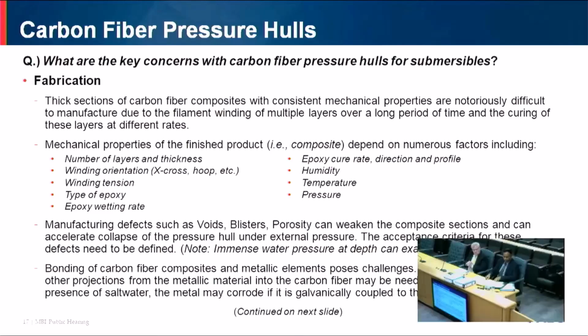Okay? So in a thick carbon fiber pressure hull, there may be several layers of carbon fiber composites, and these layers cure at different rates. So what you'll have is several layers with different mechanical properties since they were cured at different rates at different times. Okay? So manufacturing a thick section of carbon fiber composites with consistent mechanical properties throughout the thickness is difficult. Okay? So the mechanical properties of the finished product or the finished carbon fiber pressure hull depend on a number of factors. So these include the number of layers and the thickness of the carbon fiber composites. So the more the number of layers and the greater the thickness, the more difficult it is to achieve a pressure hull with consistent mechanical properties throughout the thickness.